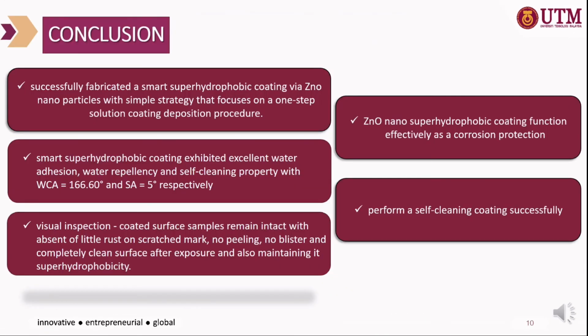To wrap up everything, this study had successfully fabricated a smart superhydrophobic coating via zinc oxide nanoparticles with a simple strategy that focuses on a one-step solution coating deposition procedure. The smart superhydrophobic coating exhibits excellent water adhesion, water repellency, and self-cleaning property with a water contact angle of 166.60 degrees and a sliding angle of 5 degrees respectively. Based on visual inspection results, the coated surface samples remain intact with absence of little rust on scratch marks, no peeling, no blister, and a completely clean surface after exposure, while also maintaining its superhydrophobicity.